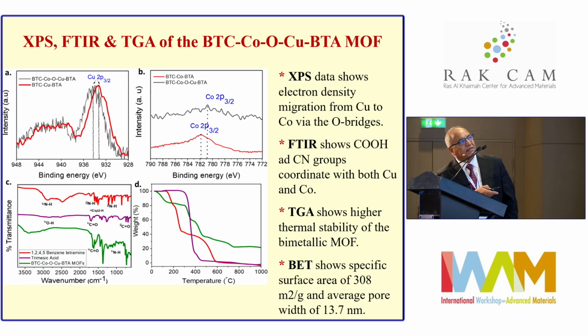So for the cobalt, you can see in the monometallic that the 2p electron is at lower binding energy, but in the bimetallic, it goes to higher binding energy. And so that indicates that there is an electron density shift from copper to cobalt.